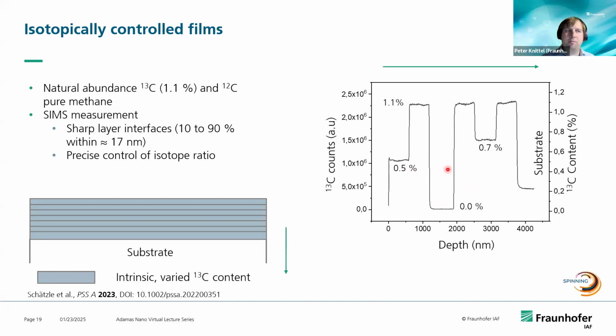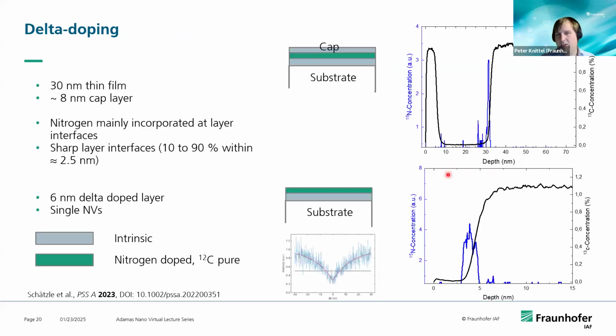For a nitrogen doped layer, it's a bit different because nitrogen doping actually increases the growth rate, which makes it a bit more difficult to reach very thin layers, being single-digit nanometers, but we can actually achieve something like 20 to 30 nanometers here, depending also a bit on the concentration that we add.